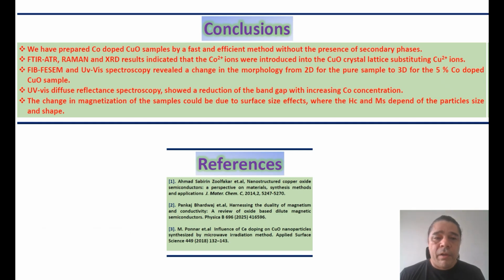Conclusion. We have prepared cobalt copper oxide samples by a fast and efficient method without depositing secondary phases. FTIR, Raman, and XRD results indicate that cobalt 2 plus ions were introduced into the copper oxide crystal lattice, substituting copper 2 plus ions. Field emission scanning electron microscopy reveals a change in the morphology from 2D for the pure sample to 2D and 3D for the 5% cobalt doped copper oxide sample.